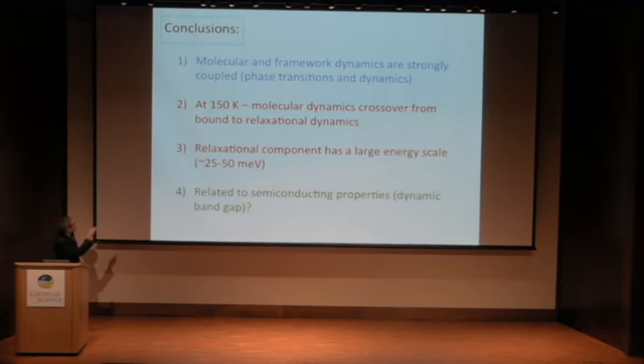Okay, so in summary, first of all, hopefully I've convinced you that the molecular and framework dynamics are strongly coupled. At low temperatures, you have this quasi-static molecular motion that gives way to this very fast relaxational component at high energies. And that happens when the framework phonon softens. So I've compared the 2 different schemes, where we have bound harmonic phonons and also this large energy scale relaxational component. One thing that I haven't talked about, but it would be speculative, is whether this large energy scale in these relaxational dynamics is associated with the nice semiconducting properties, in particular the long diffusion lengths and also the large time scales. So anyways, thanks very much.